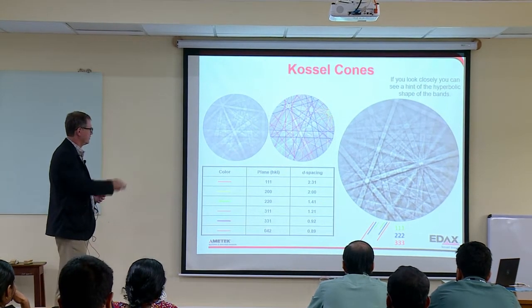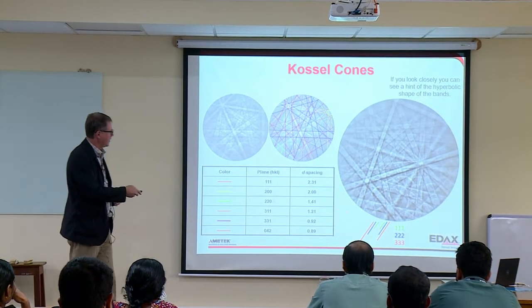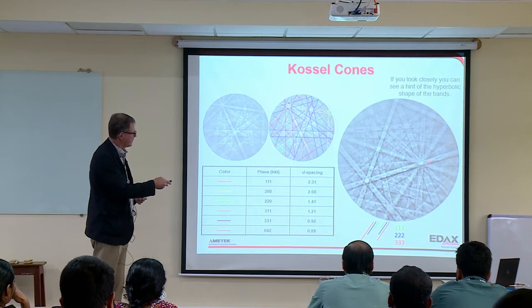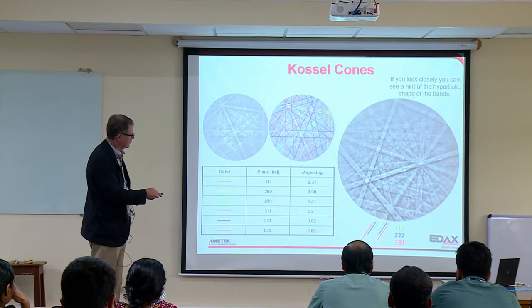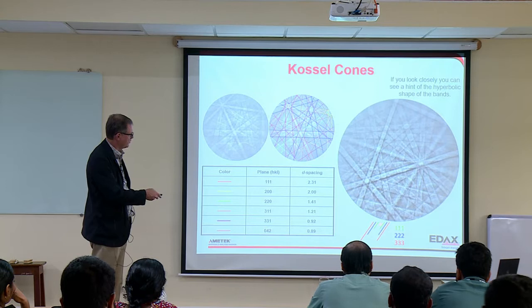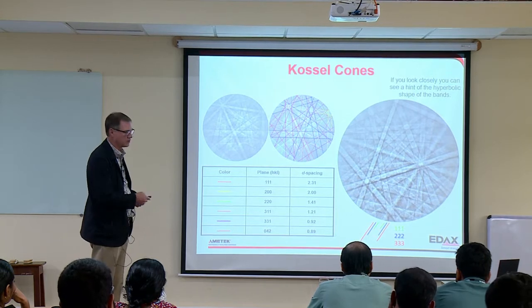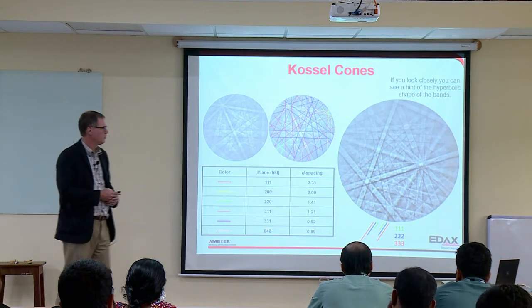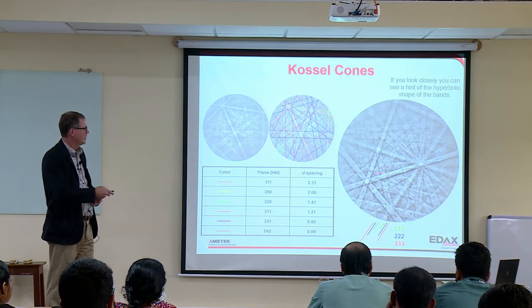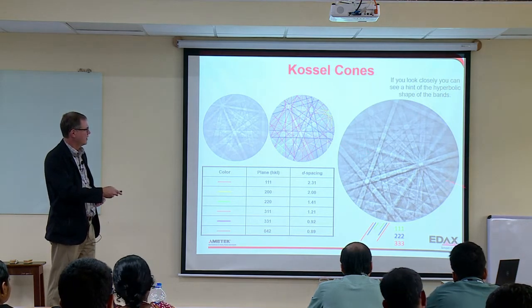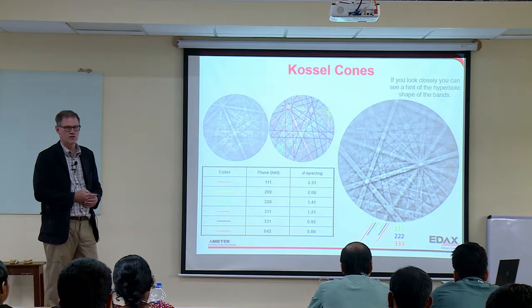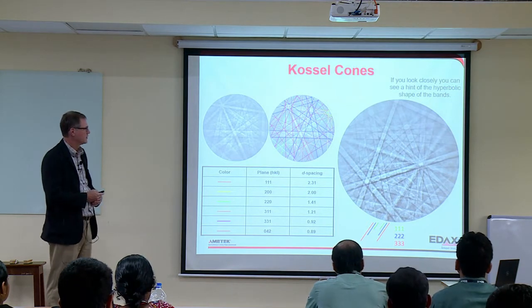This one is from nickel, sorry. And if you look here in the silicon, there's a very nice pattern. You can actually see multiple orders. So you have 111 planes, 222, 333. So you can see multiple orders of material. And the solid angle we're capturing here is about 70 degrees approximately, at least typically.